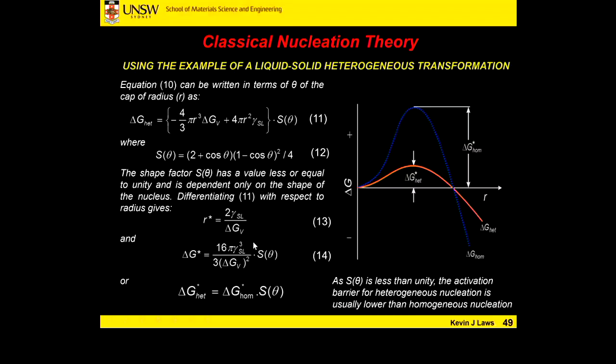I'm not going to go through all of these equations here, but this is the general takeaway that we get for heterogeneous nucleation. As I said, this is a good learning for you for phase transformations with Michael Ferry or whoever's teaching it now for next year, but the information's there if you're interested. But the key takeaway: our delta G is much, much smaller for heterogeneous nucleation. So classic nucleation theory is explaining what we see in nature with regards to a heterogeneous nucleation site. Lower energy.